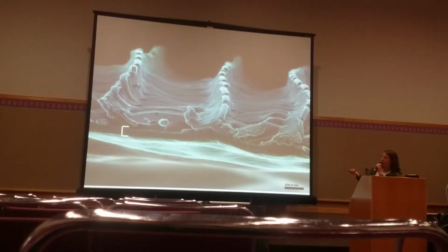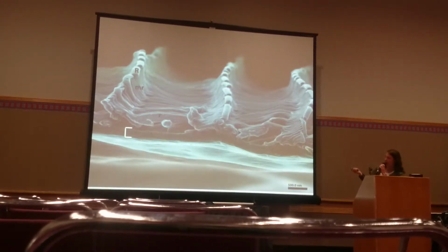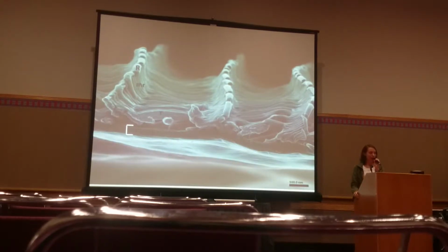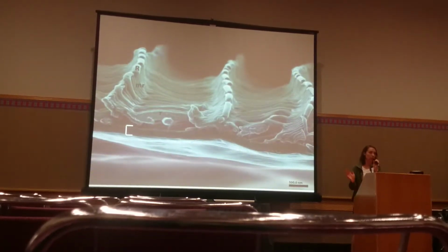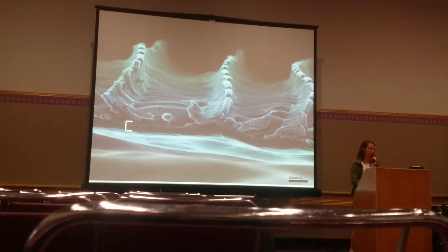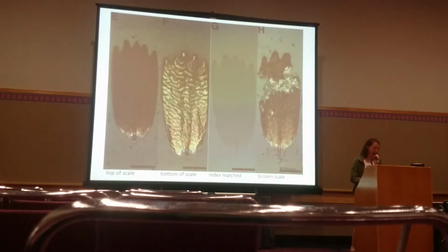However, if we measure the thickness of the lamina, so that's this thickness here, it's 210 nanometers thick. And actually that is the right thickness to make blue just as a simple thin film reflector, which is that simplest case I explained at the beginning. So how is that different structurally from wild type, or is it just simply a loss of a dark pigment?